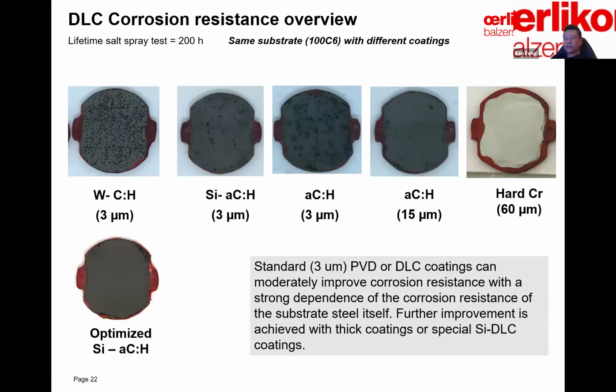Sometimes the corrosion resistance of the coating material is very important. The PVD coatings are really thin and have some natural porous structures, so they will allow some corrosive substance to go through the coating and start corrosion at the substrate and coating interface. At that point, your coatings will start to come off. So there are a couple of ways we can improve the corrosion resistance of the coating. For example, we can increase the coating thickness. And as you can see in this standard salt spray test, that improves the corrosion resistance.